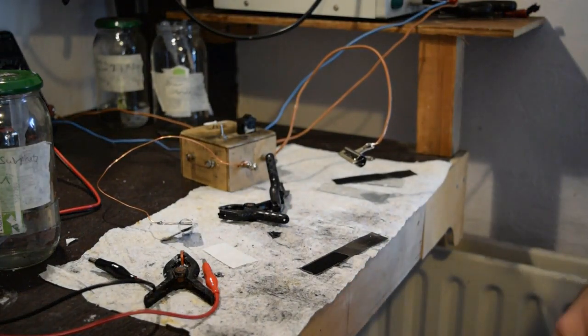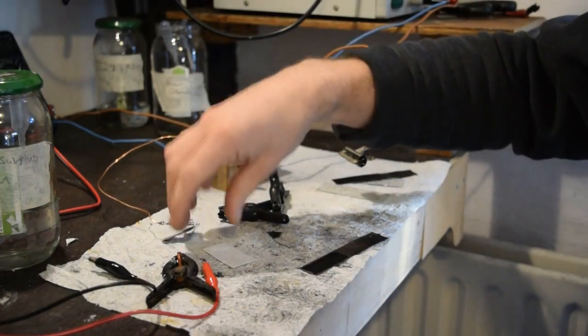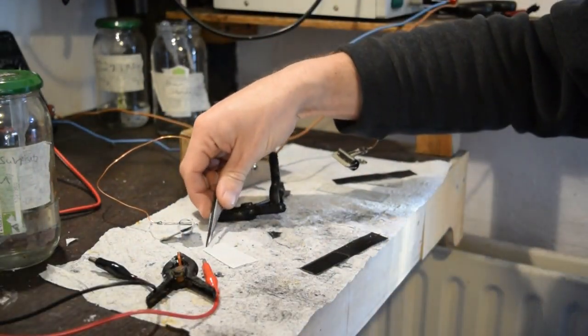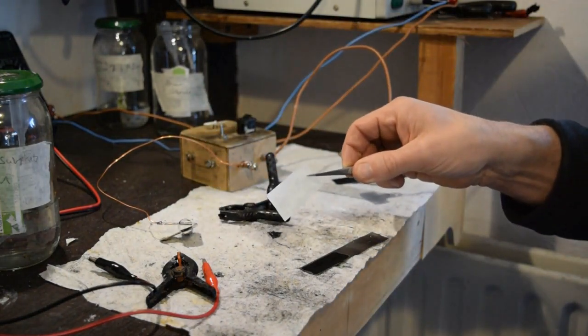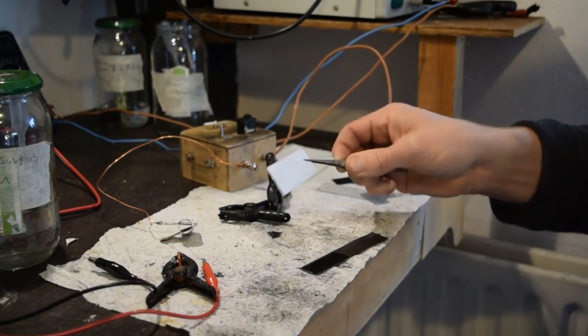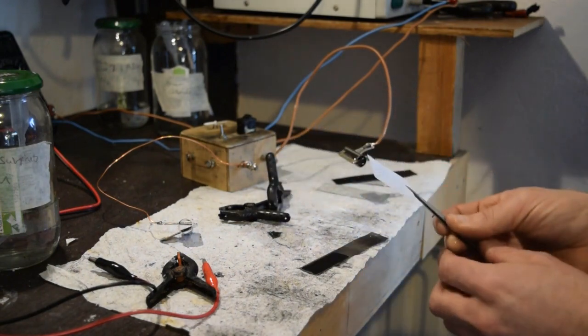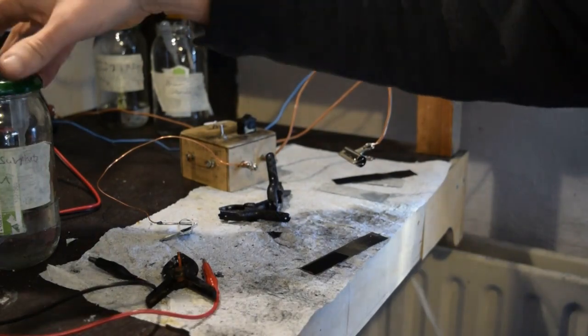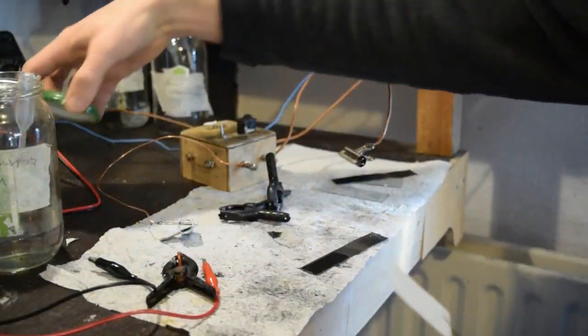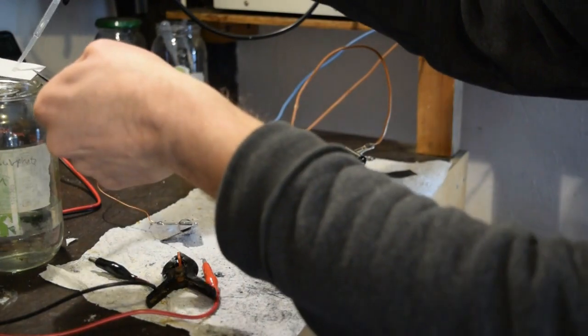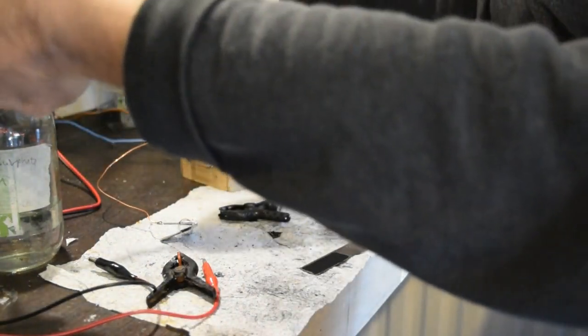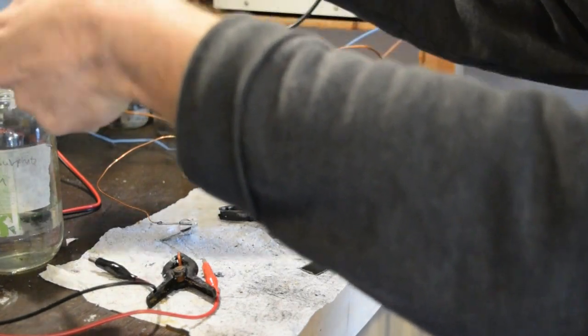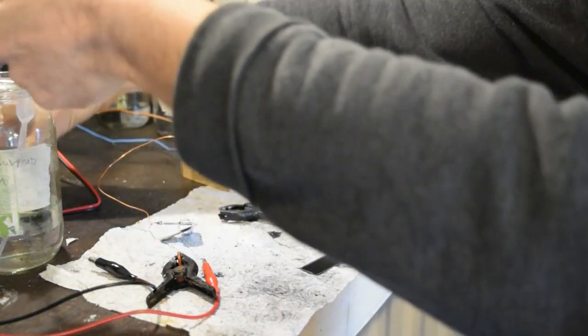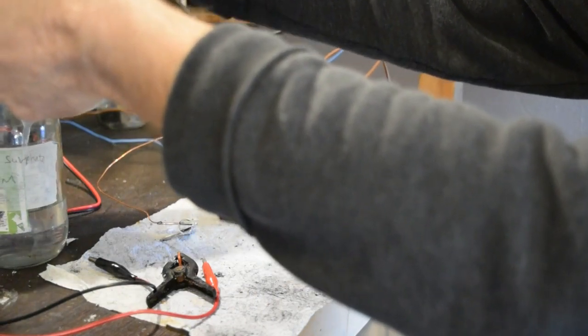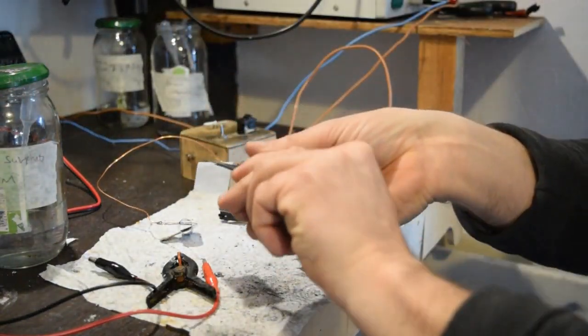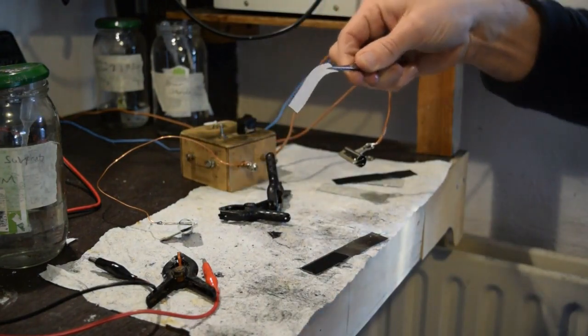And the other thing that I like to keep the same is the separator. This is just an ordinary bit of coffee filter paper, which I find works pretty well. Also, obviously, you keep the current collectors the same, the graphoil as well. And what we do is we charge this to 1.6 volts. I usually find if you try to charge it at 1.8 or above, I find that the cell starts to fail after about 10 charges and discharges.